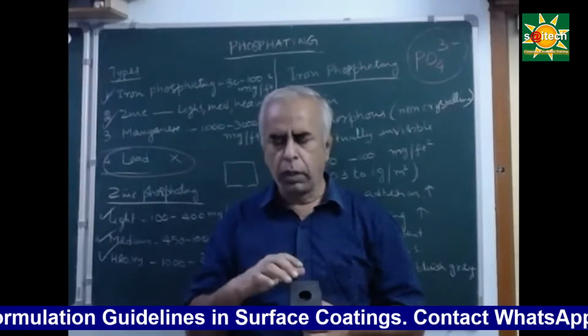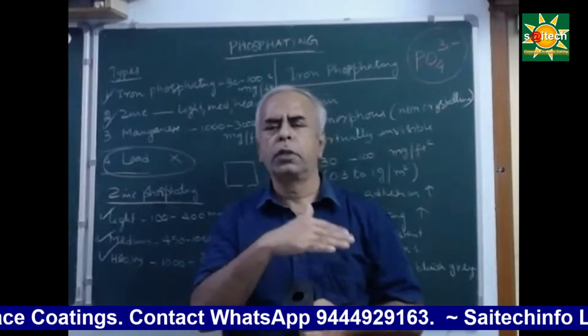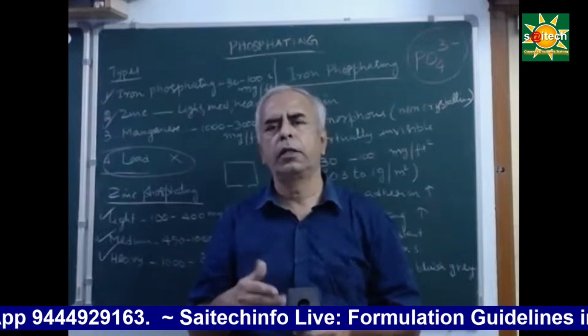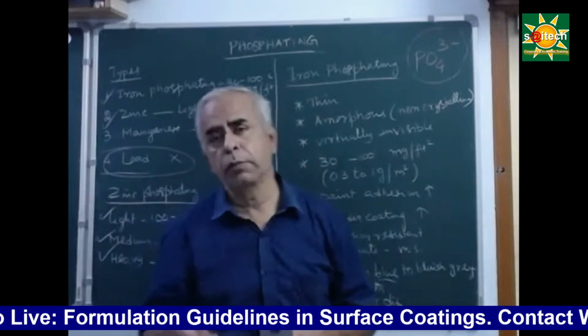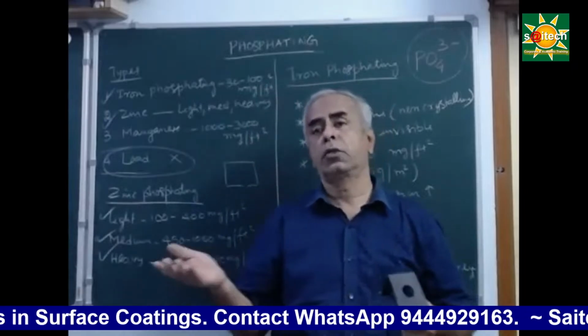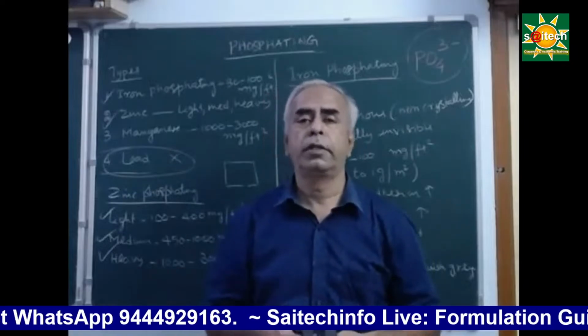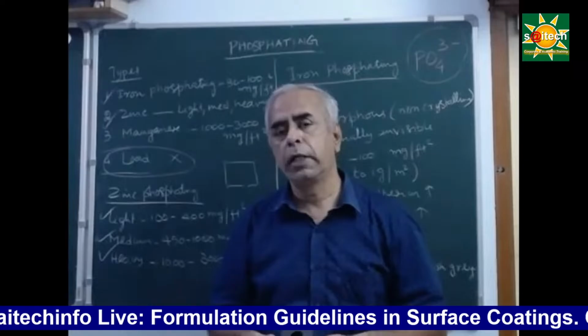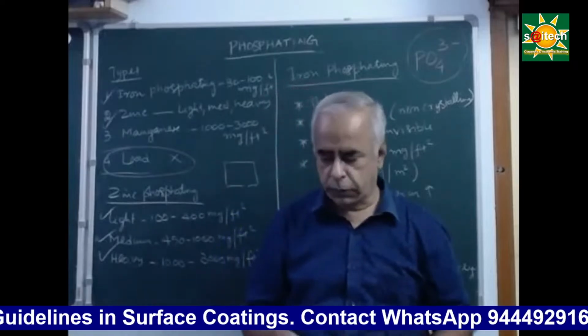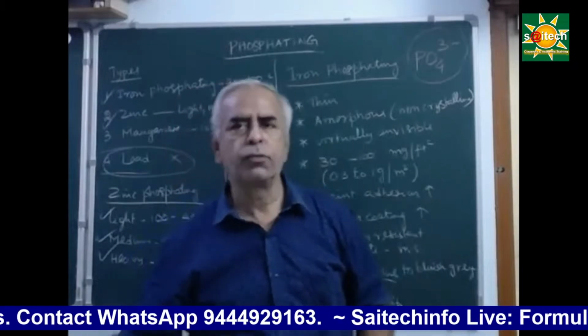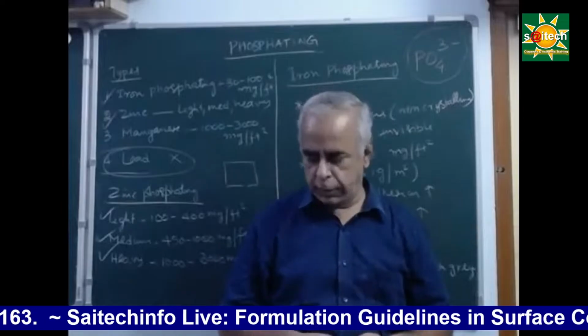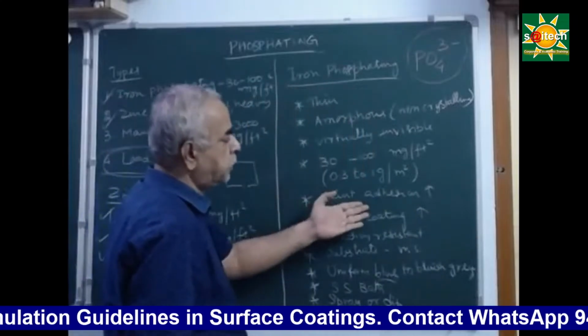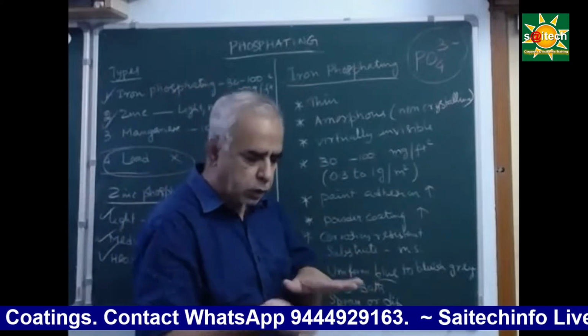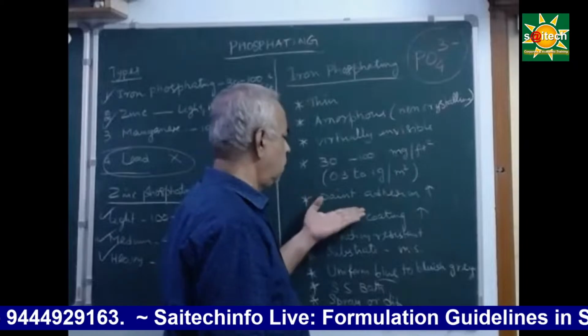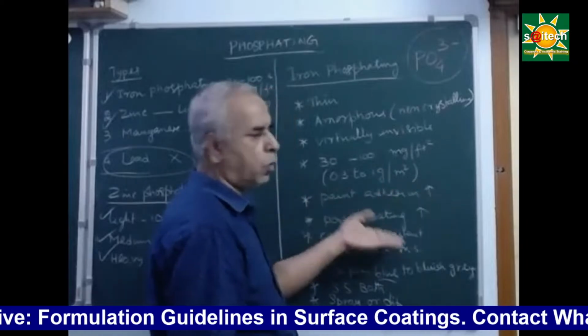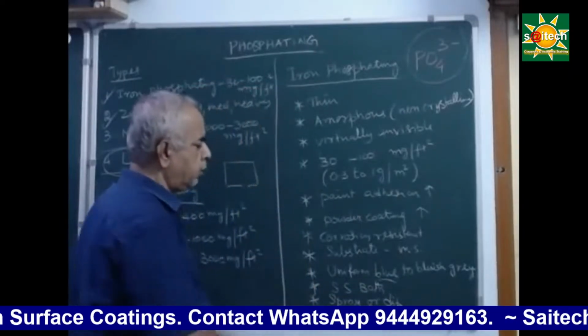For certain components they may insist on 100 or 200 hours, in some cases 400 hours, in some cases 600 to 800 hours. In the case of tractors and other heavyweight equipment, machineries and automobiles, they may even go for 1000 hours of salt spray. So based on the type and nature of coating, the corrosion resistance can be enhanced. Now the paint adhesion can be improved with the help of this iron phosphate undercoat. When I say paint adhesion, I mean adhesion of liquid paint as well as powder coating. Then, as I already mentioned, corrosion resistance.